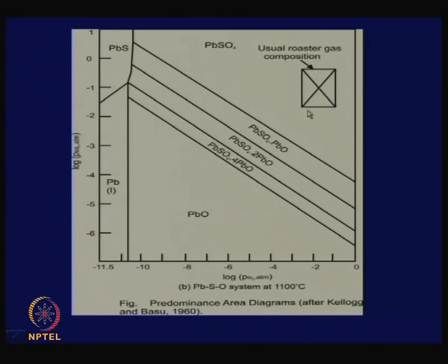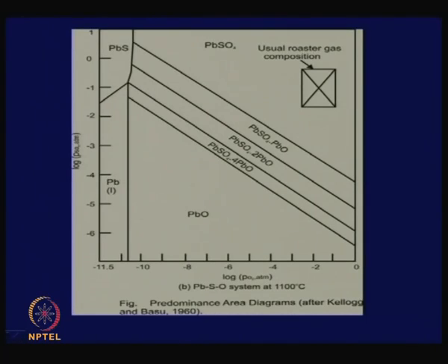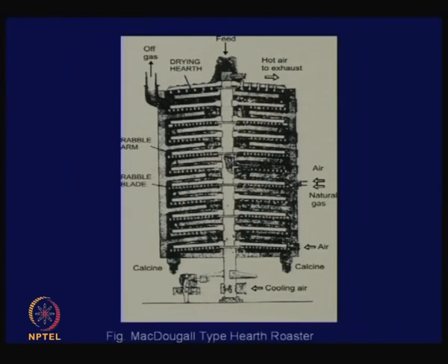Now, this sort of calculation gives us the limiting values, that this is the equilibrium value. Obviously, if you get an equilibrium temperature of T, the actual operation in the industry would be at higher temperatures for various reasons. Firstly, to accelerate the rates or sometimes to melt different phases, but we still want to know the limiting values that will tell us exactly where the operation should be carried out.